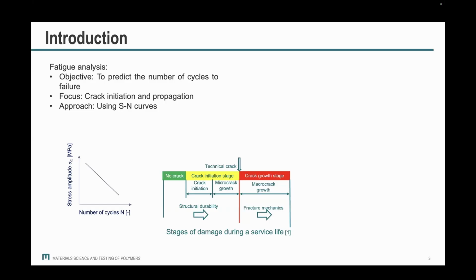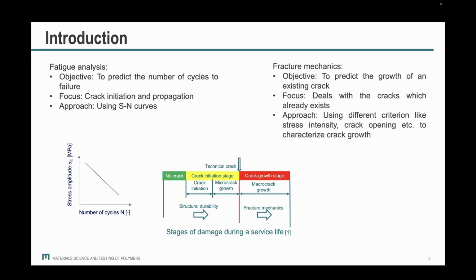But as soon as we have a technical crack in the component, we have to switch from fatigue analysis to fracture mechanics. In fracture mechanics, as I mentioned earlier, we want to estimate the number of cycles before we have a failure in the component. We have also for fracture mechanic analysis different tools, but one of the most favorite ones is the stress intensity against the crack growth rate, also crack kinetic curves.